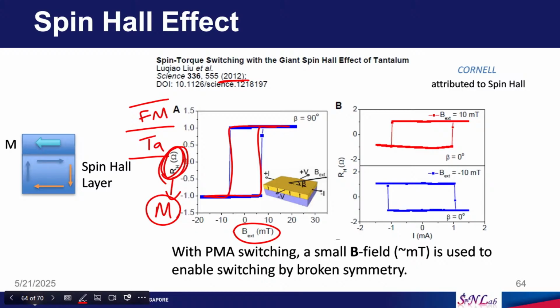So, in this study they are measuring the magnetic properties of this ferromagnetic layer using anomalous Hall effect. At first they demonstrate that this magnetic material shows a hysteresis loop like this. Okay. So, in the next slide what they do is they send a current through the tantalum layer. Here there is a little bit of external magnetic field, but this is fixed, this one is constant. It is not changing when they do the experiment. So, what they change is the current they send through the tantalum layer.